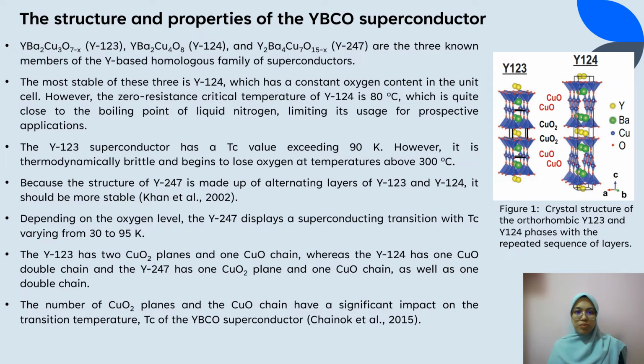The structure and properties of YBCO superconductor. Y123, Y124, and Y247 are the three known members of the Y-based homologous family of superconductors. The most stable of these three is Y124, which has a constant oxygen content in the unit cell. However, the zero-resistance critical temperature of Y124 is 80 Kelvin, which is quite close to the boiling point of liquid nitrogen, which is limiting its usage for prospective application.